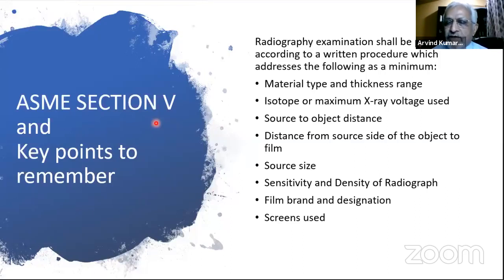If the procedure doesn't talk about thickness range, I might be using a gamma ray for 100 mm thickness also, which is not permitted. Gamma ray generally is from 10 mm to 65 mm, which is the right range where you can do gamma radiography, if it is with iridium 192. If it is cobalt, you can go up to 5 inches also. So if the thickness range is not mentioned, you are not able to decide whether my procedure is going to work well or not.